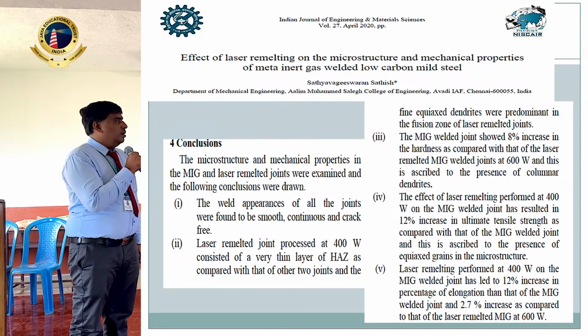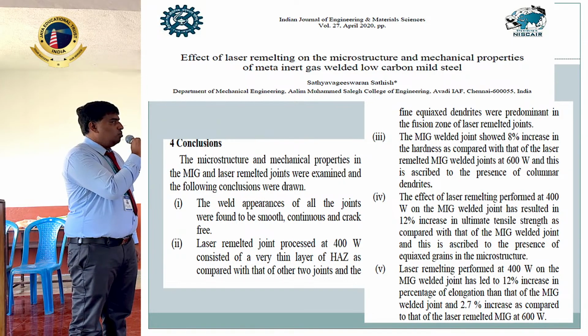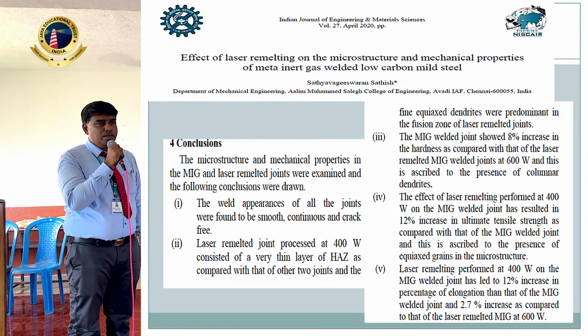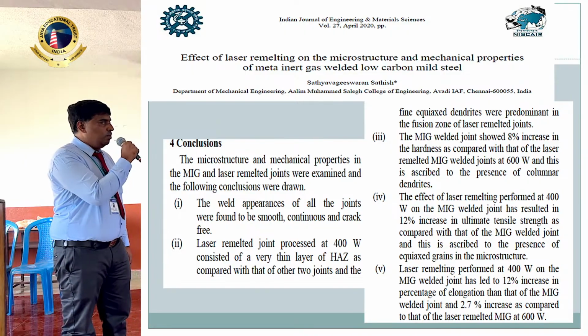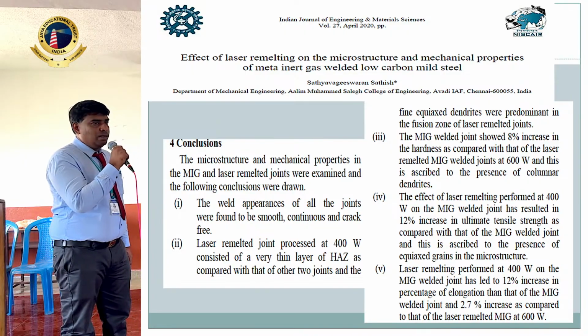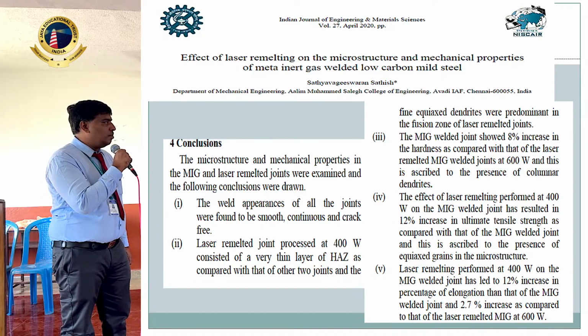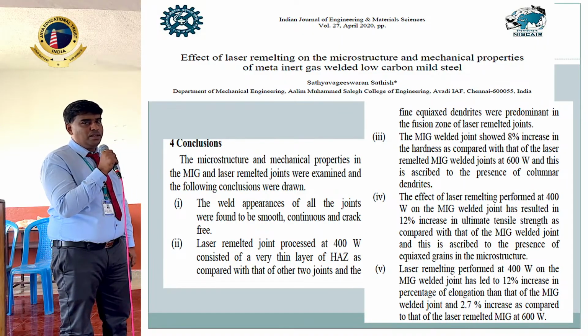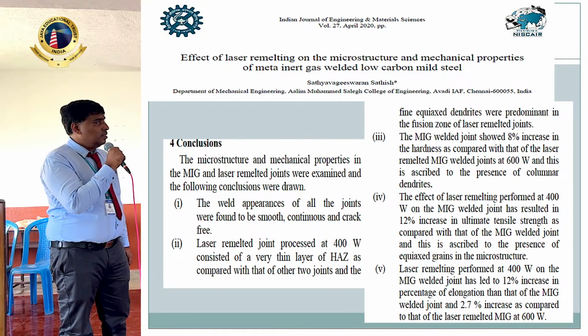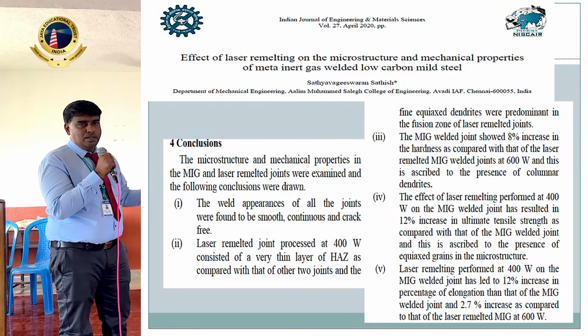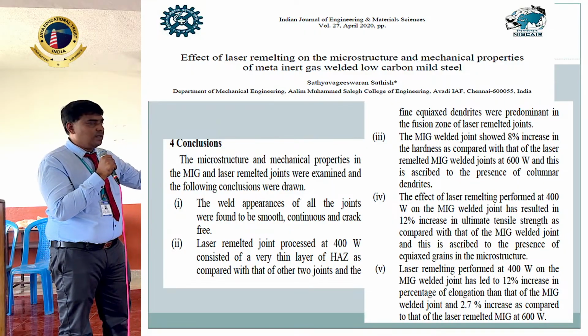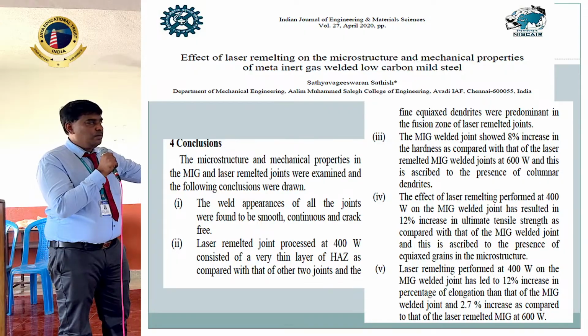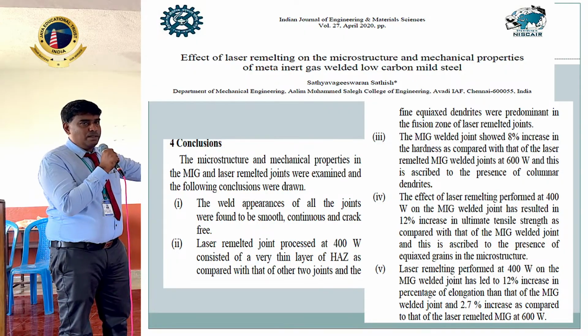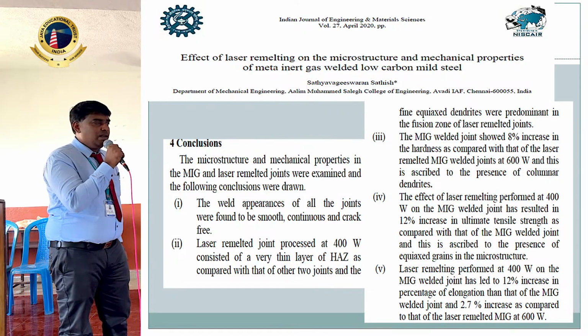If you look at the conclusion for this paper, here already I told about this work. So MIG welding was done on low carbon steel. The grain size was found to be very coarse, which in turn has reduced the mechanical property. So we have used several methods, among which laser remelting was not at all performed on this particular low carbon mild steel. So we are the first to work on laser melting on MIG welded mild steel, and we observed some grain refinement.